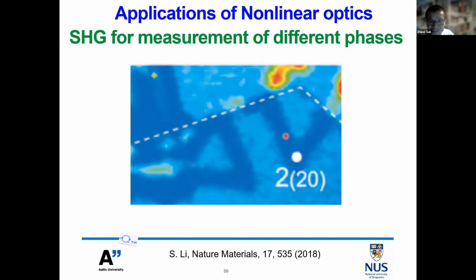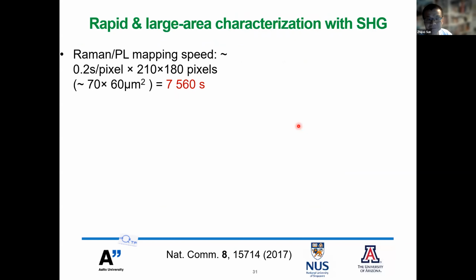You can see here, we didn't see strong second harmonic generation because, as I mentioned, the bilayer MoS2 has a centrosymmetric structure, which doesn't give you second harmonic generation. So with this method, you can clearly tell the different phases inside of the flakes made by different deposition methods. We also know that Raman and photoluminescence can be used to check the grain boundaries.